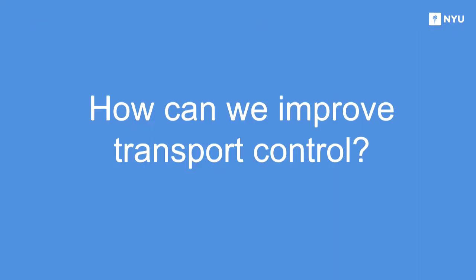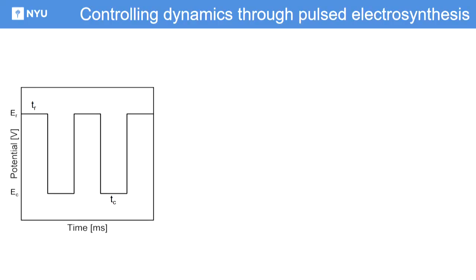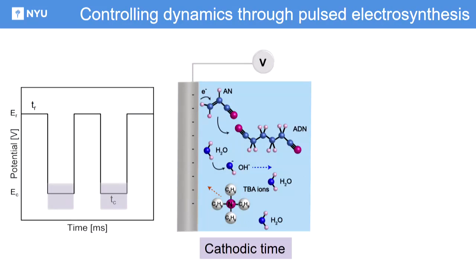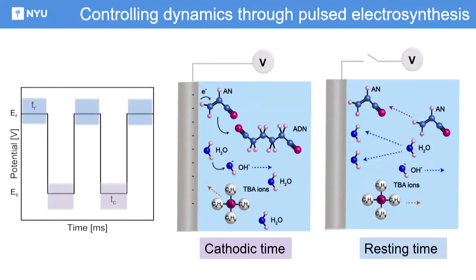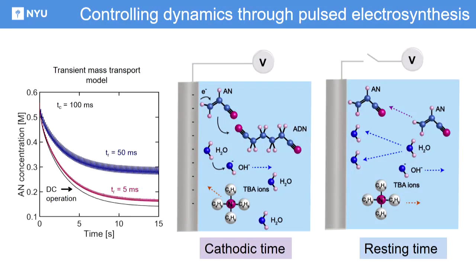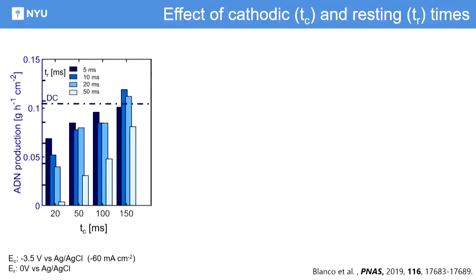And we started to wonder, how can we enhance the transport of these reactions? And then we just use an old trick in electrochemistry, it's pulse electrosynthesis, where we can apply a pulse, where we do a cathodic reaction during a certain time, we produce the molecules that we want. As the reactant starts to deplete at the interface, then we stop the reaction, and then we allow the reactant to back diffuse. And in that way, we can control the concentration at that interface. We can use continuum models to guide us onto windows of time frames in which we can control this concentration, and then we can run these reactors under dynamic conditions. And these are sort of the results that you get.